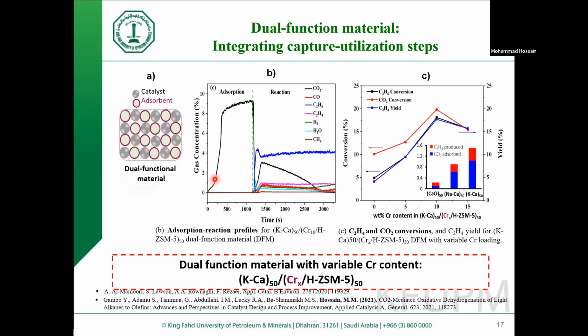This figure shows the uptake of CO2 by a material here. This is a basic material. And then when the CO2-adsorbed material was exposed, that CO2 interacted with hydrocarbon to give different products. So here you can see the storage of CO2 on the basic material can play a significant role in achieving good conversion and selectivity. And of course, one has to take into account the concentration of CO2 in this case, and maintain a proper ratio of hydrocarbon and CO2.